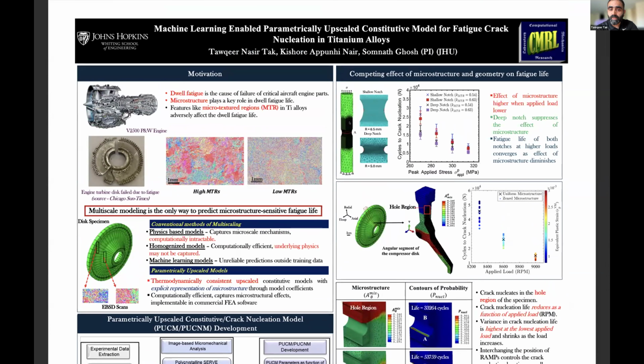So applying this model to a notch specimen to explore the effects of the microstructure and geometry, we take a double-edged notch specimen where we have two different types of notch. One is a shallow notch, another is a deep notch. And we assign two different microstructures, for which we assume the signature as microtexture intensity. Here we see in general the cycles to crack nucleation come down with increasing load. But we can see the effect of geometry as well as the microstructure.